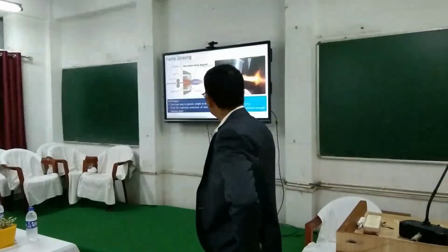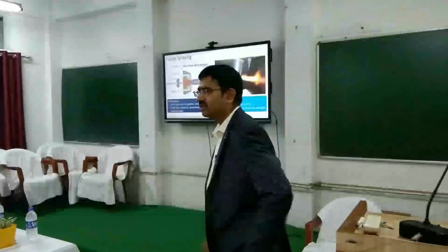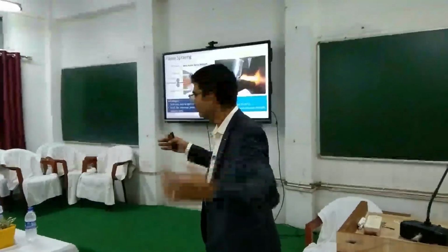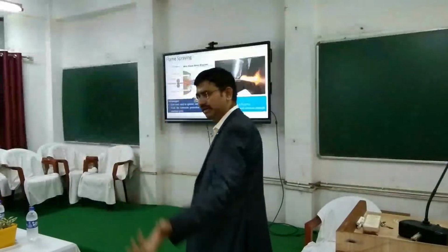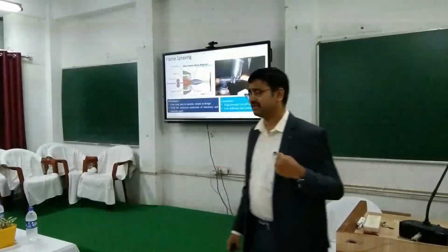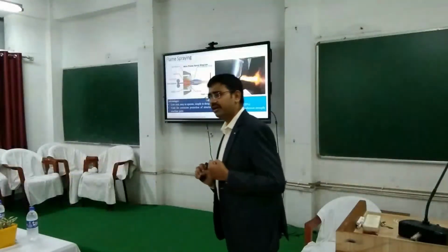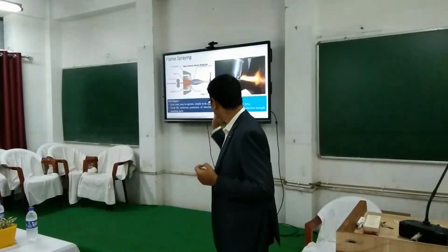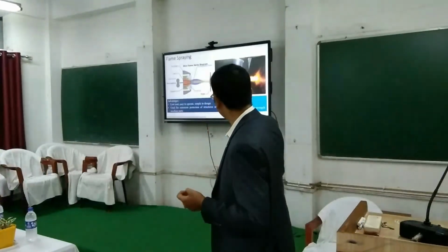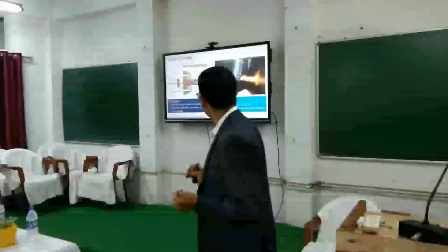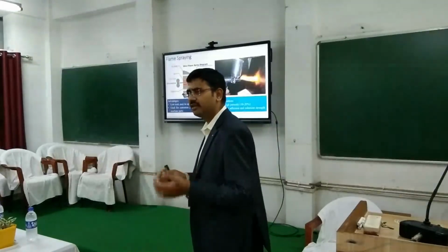One limitation of this process is the porosity is very high. The coating will not be extremely dense because you are not completely melting the particles. The velocity of impact is less. So basically you can have higher porosity, around 10 to 20%, and low adhesion and cohesion strength. A little bit, you might have some problems.